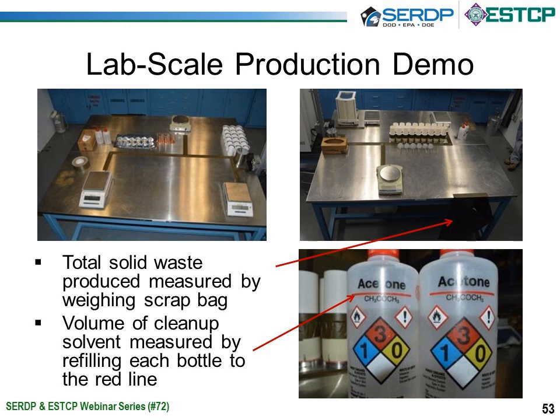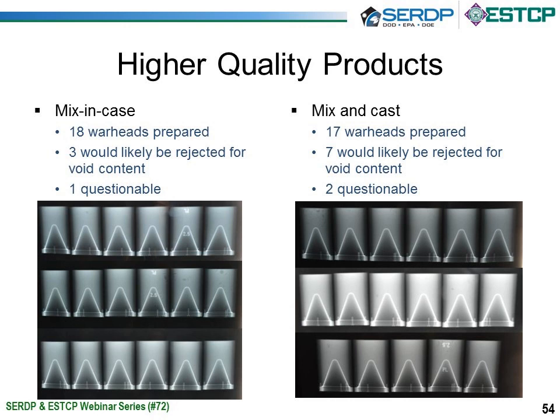If we move on to slide 54, we're getting higher quality products using this mix-in-case paradigm than what we got out of our mix-and-cast. On the right-hand side of your screen is the material that was mixed in a Baker Perkins bowl and then cast in a separate operation into the warheads. For those of you that are on the line, you can probably guess as to why we only made 17 warheads in this operation and 18 warheads in the mix-in-case operation. I did not account for the material that was going to be hung onto the sides of the bowl or onto the sides of the blades in the casting operation, and so we ended up with one less warhead.